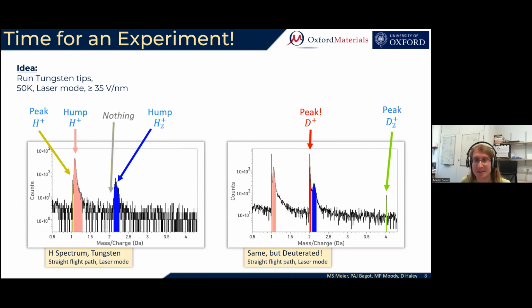And what this is telling us is this: the fundamental field evaporation of hydrogen or deuterium out of our sample has not changed. The deuterium from the sample, we are still evaporating and detecting it precisely with the energies and times of flight that we would expect. The energy deficit seems to be something that is exclusive to the contaminant hydrogen signal.